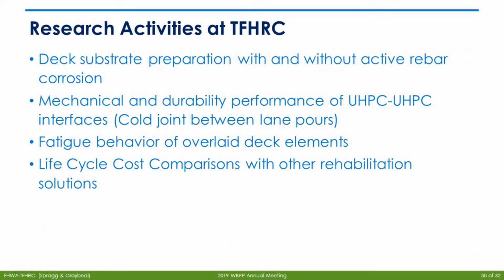So as far as research activities that we're doing at Turner Fairbank, we are looking at substrate preparation methods with and without active corrosion in your rebar. There's been some concern about whether you have to excavate the rebar and stop the corrosion and then put your overlay, or some people say the UHPC overlay will keep out any moisture or oxygen, which could kill the corrosion reaction, so we're investigating that.